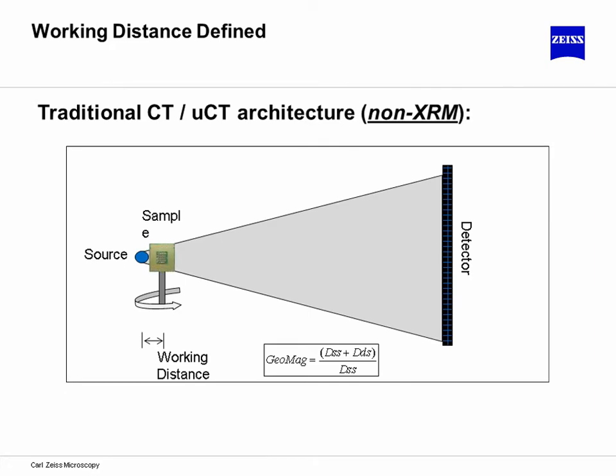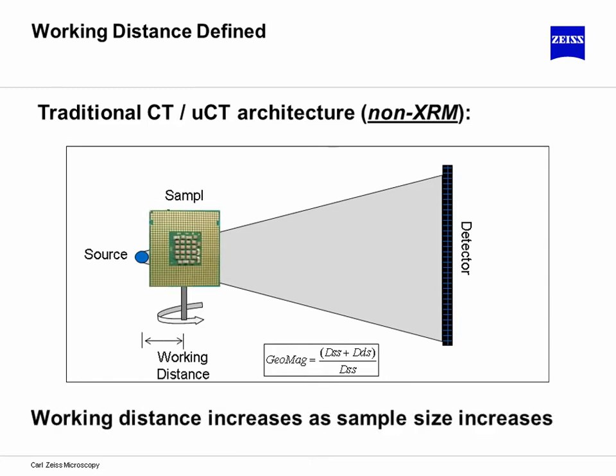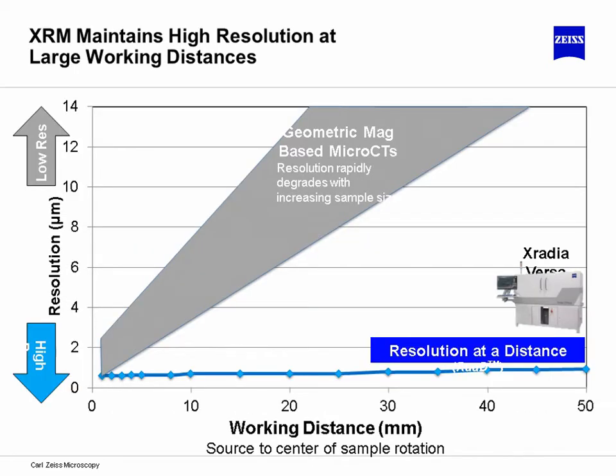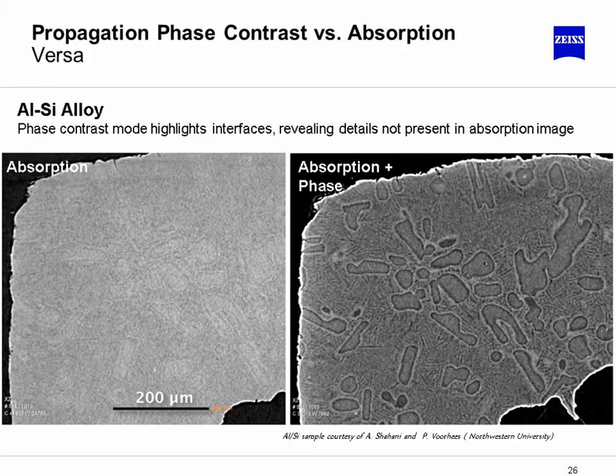Now, critically, the sample dimension is of most concern in conventional micro-CT, whereas when the sample grows, it will typically require you to change the working distance so that you're now further away from the specimen on the rotation axis, which effectively degrades your ultimate resolution that you can achieve. That's circumvented in the Versa design, where you effectively have constant resolution of a micron or less over a long range of different working distances. So you're invariable to that effect.